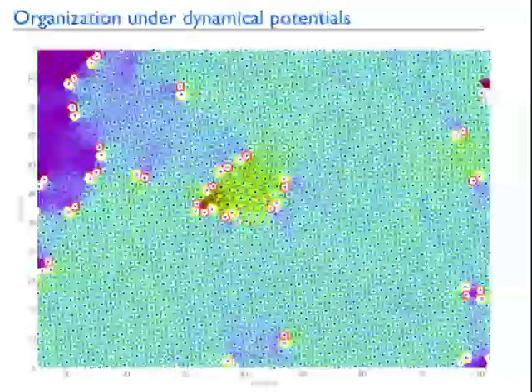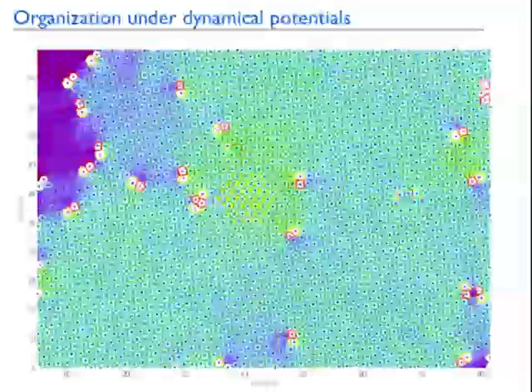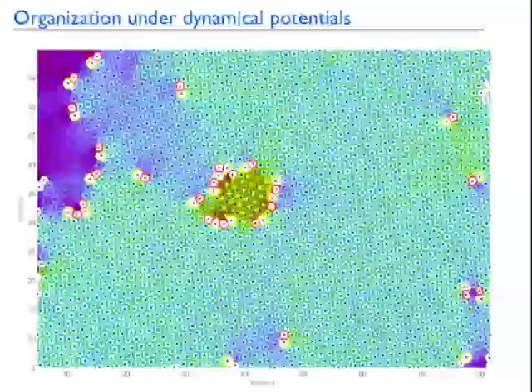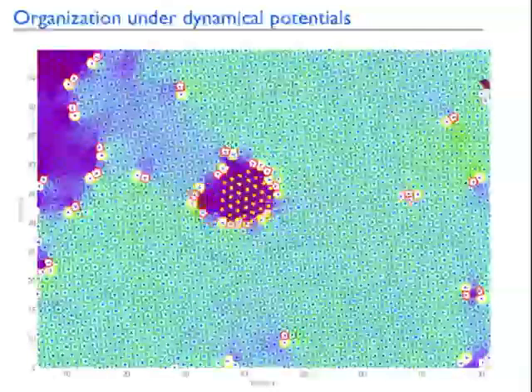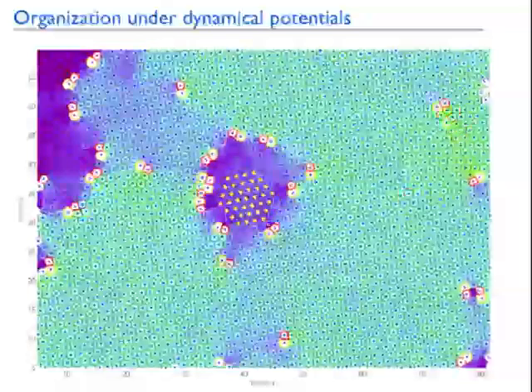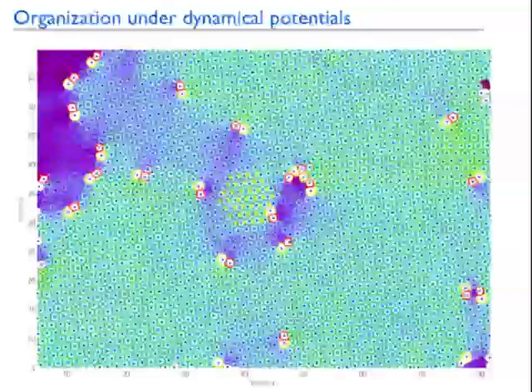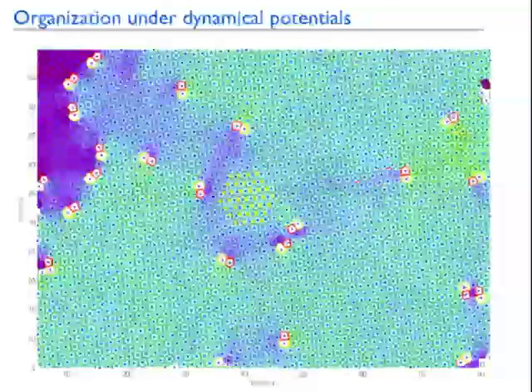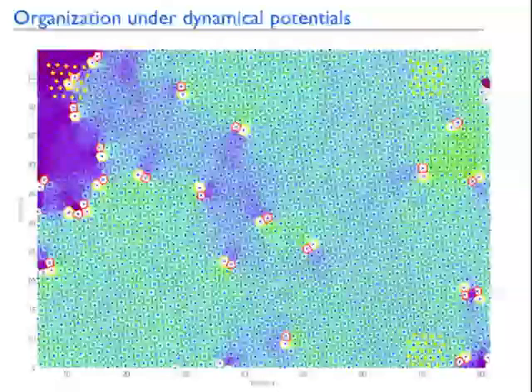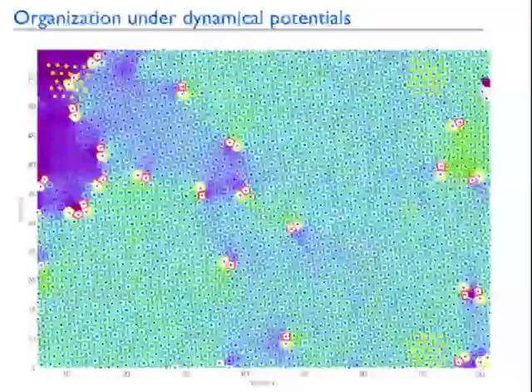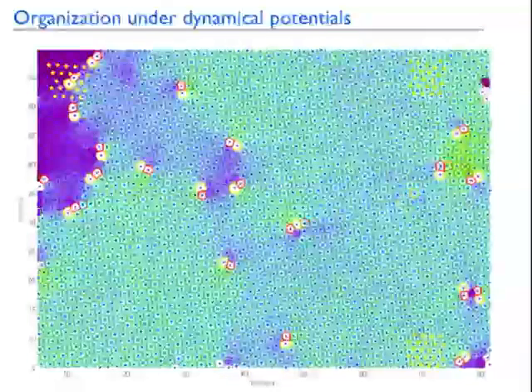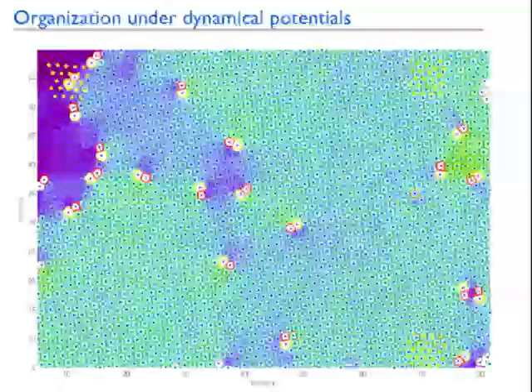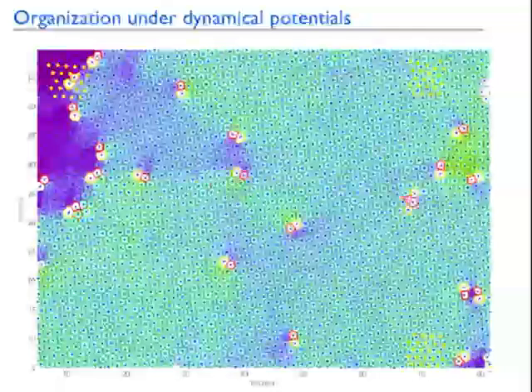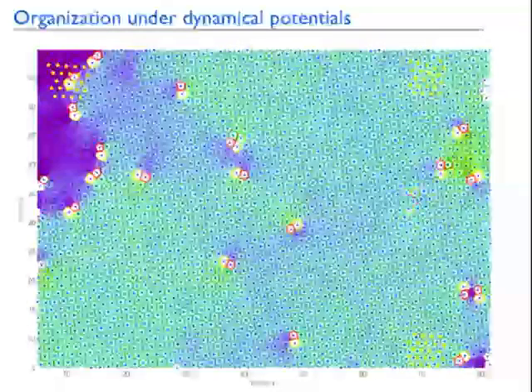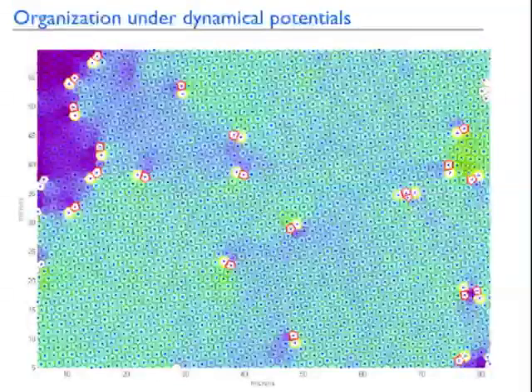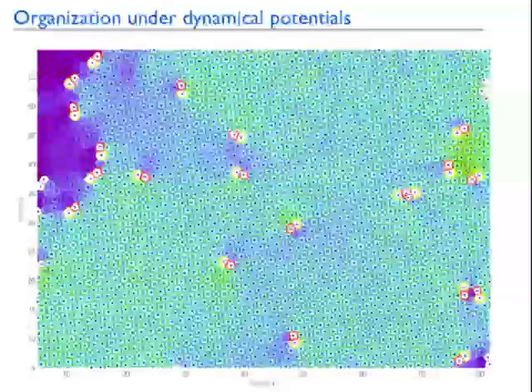Now it's going to go back, and here it's rotated by 60 degrees and should be perfect again. So you might have expected that they would annihilate. Now we're going to rotate it back, and you might expect, at least when you rotate it back, that it should annihilate. But the answer is, it turns out, the angle between two regions of a solid depends on the density of dislocations. So if there are no dislocations, the orientation over here and the orientation over here are the same. If I have a few of them, I rotate a little bit from here to here. If I have 30 degrees between them, then I have to have the region completely surrounded by dislocations which are touching, because the maximum rotation is 60, okay? So now what you expect is, I rotate this way, I'm going to be at 30 degrees completely surrounded. Now when I rotate back, they should annihilate.